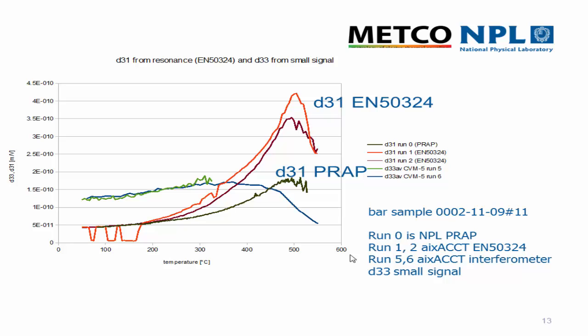But here we're seeing quite good correlation between the temperatures at which the peaks occur. These have both been measured at similar values of electric field, and we're seeing quite reasonable repeatability between different samples. So with similar types of measurements under controlled poling procedures, we get some consistency in results.